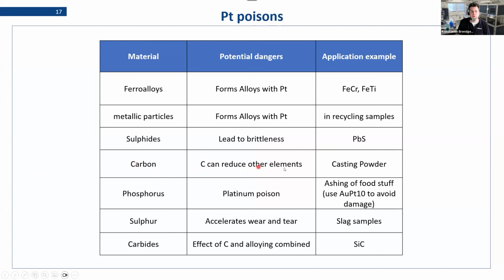Carbon is another problem because carbon can reduce other elements. For example, carbon in a casting powder can lead to other elements in the sample being reduced back to the metallic state. And then we are back up here. We have a poison that forms an alloy. Phosphorus is known to have this effect of, again, making the surface very brittle and leading to a lot of wear and tear and the need to be recycled very often. This happens in foodstuff, and one way around it is to use a different platinum gold alloy. They actually recommend that if you're using phosphorus samples in the food industry, use platinum gold 90/10, because that seems more resistant to this effect in comparison to our 95.5%.